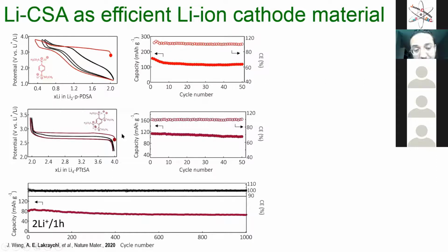And even better, with this molecule you can cycle at high rate. Here we are talking about exchanging 2 lithiums in 1 hour, and you can do that during 1000 cycles. So this one is very, very promising. We do have other examples based on this molecule with sodium, magnesium, potassium.